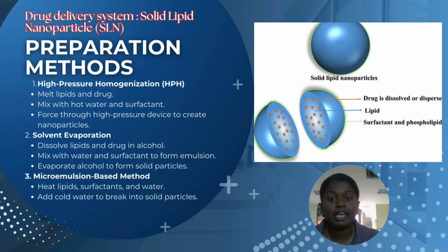Next, we have the microemulsion-based method, whereby the lipids, surfactants, and water are heated up to form a microemulsion, a clear and stable mixture. Once formed, cold water is added quickly, causing the microemulsion to break into tiny solid particles.